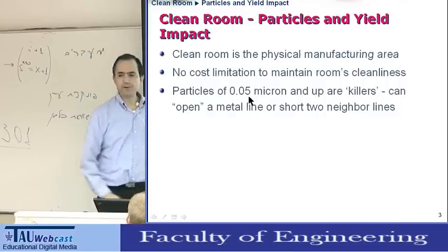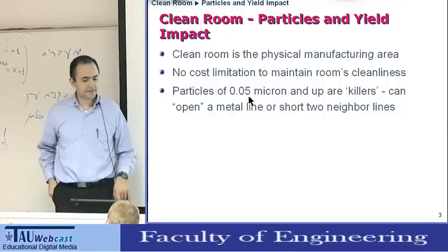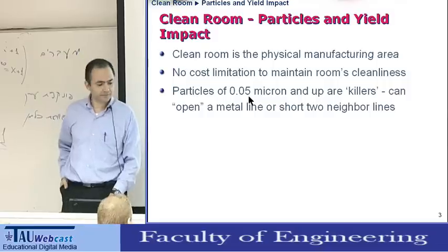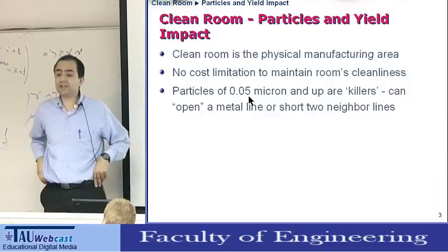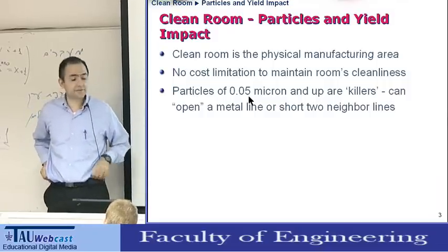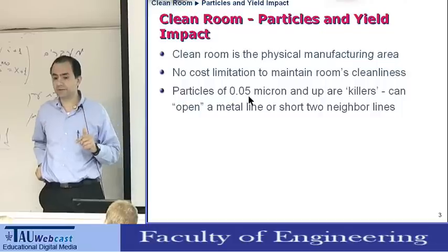Particles as small as 50 nanometers, this is 0.05 micron, can kill, and actually are killers. In today's technologies, even smaller particles can be killers.